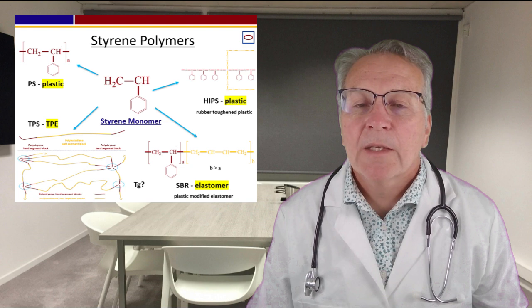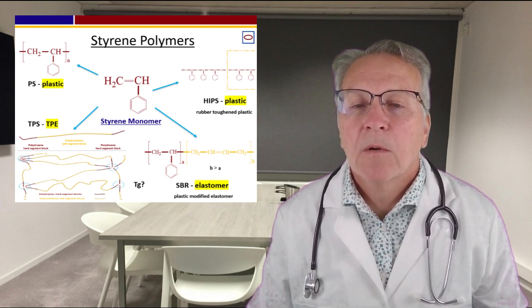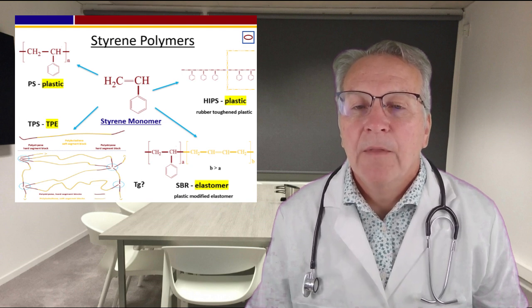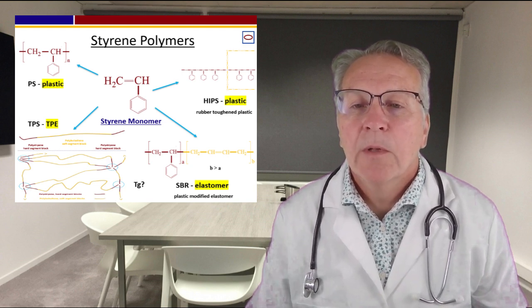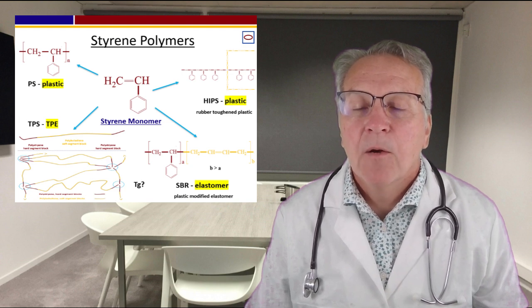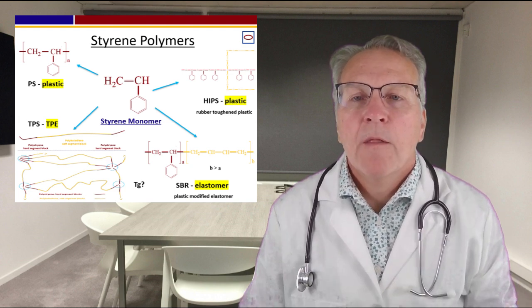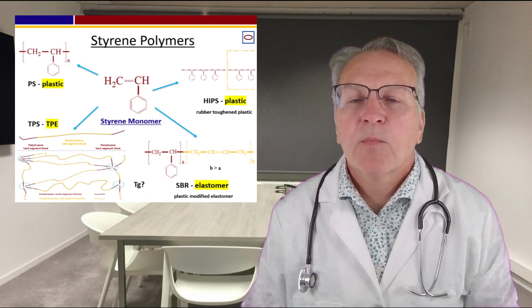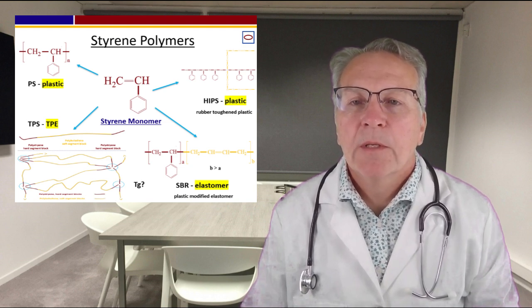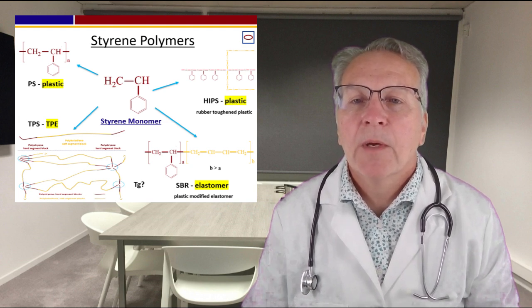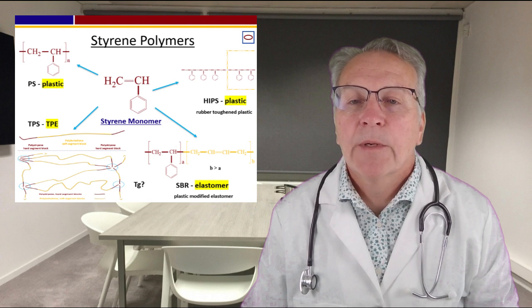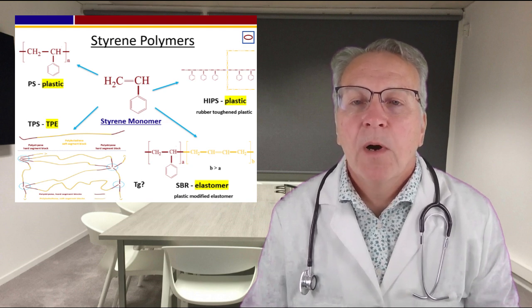TPS, being thermoplastic, cycles like polystyrene with maybe a 20-second cycle to injection mold small parts, in which the polystyrene hard segment blocks will flow with heat, and these segments will find each other upon cooling and become the hard segment anchor points. The polystyrene levels of the TPS provide the upper modulus and temperature limits, just like the rubbery butadiene provides the lower temperature flexibility limit, and it is Tg that limits where TPS will remain a flexible polymer.